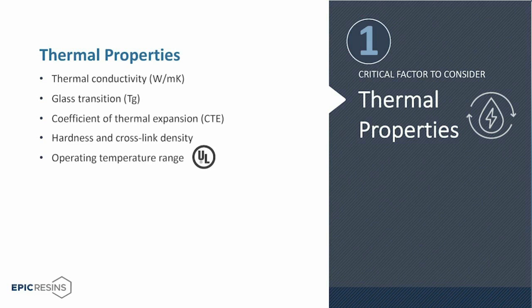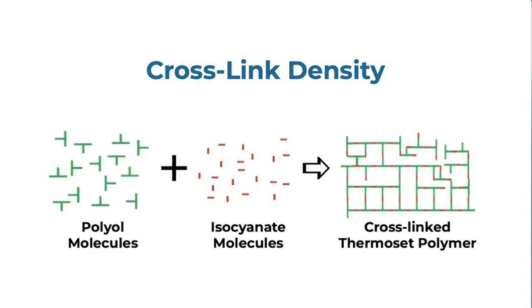Cross-link density is a term used to describe the covalent bonds in a thermoset polymer. Higher cross-link density polymers have higher hardness and thus higher TGs than lower cross-link polymers. So this is a very simple graphic that I have up talking about the cross-link density of a polyurethane. So you see polyol molecules that are mixed with isocyanate molecules on the left reacted onto the right portion of that slide where you see cross-linked thermoset polymer. And you can see those cross-linkings give the material or the polymer rigidity. As you have more cross-linking, again, you have higher hardness and greater TGs.